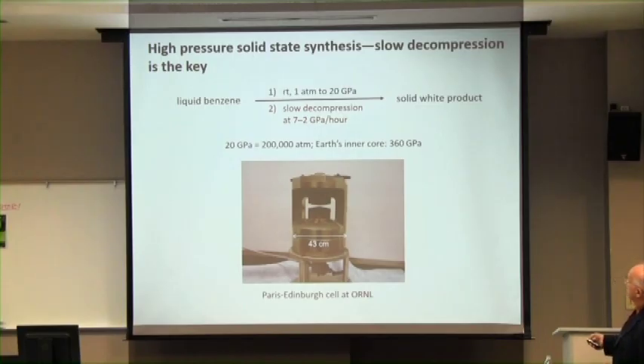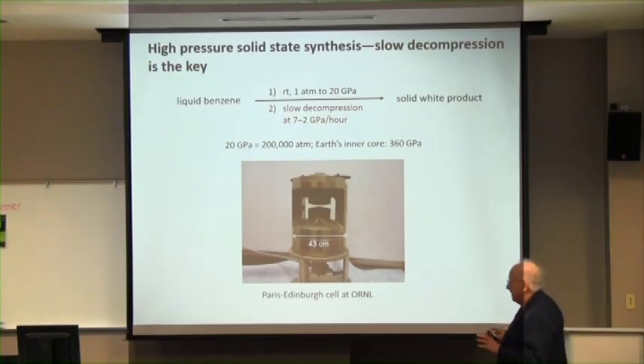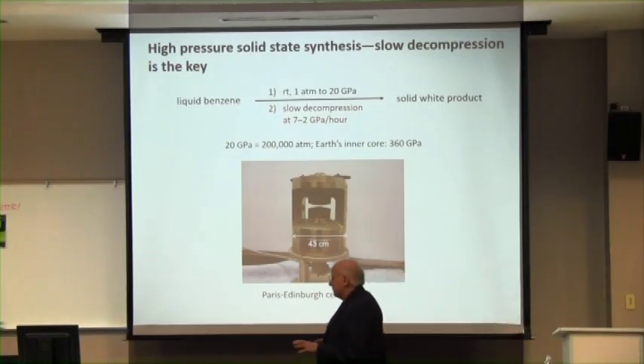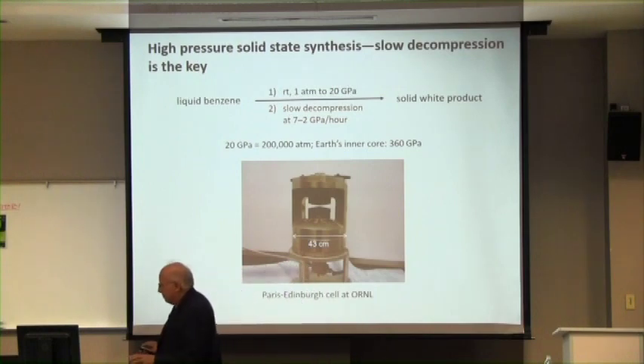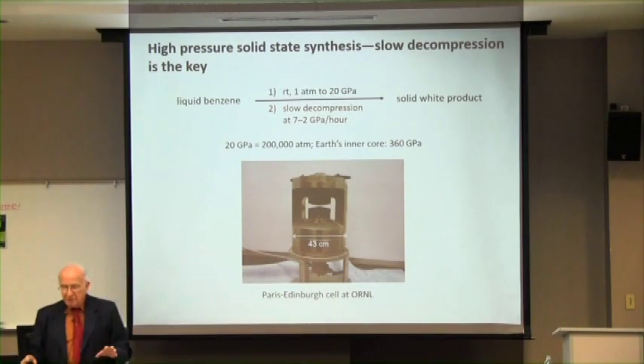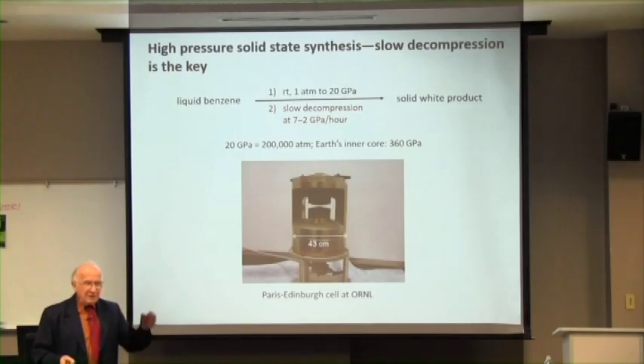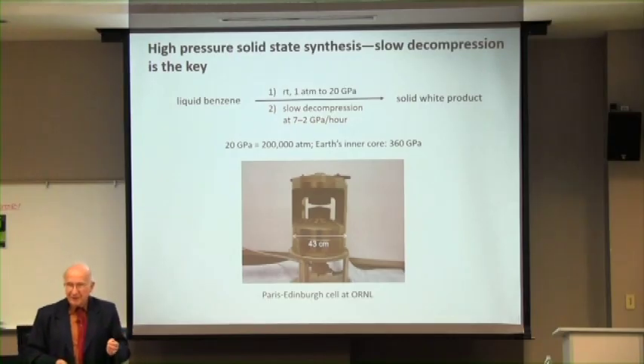It's at Oak Ridge laboratory. And they compress this to 20 gigapascals. That's the unit: 1 gigapascal is 10,000 atmospheres. So 20 times what Bridgman had. And then the key was that they did what anyone in their right sense who would be doing a synthetic procedure should do, and which metallurgists could tell them that you have to do: you have to anneal, you have to do things slowly. You don't just quench the thing. If you quench the thing, you're going to get a glass, an amorphous solid, cracks, everything else.